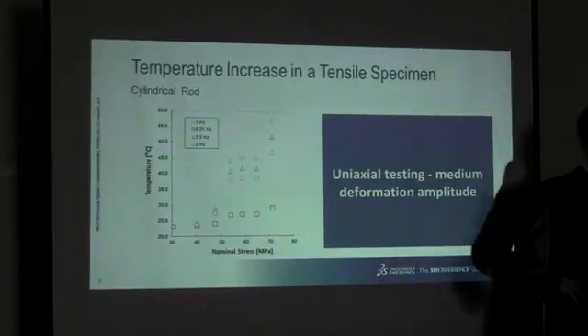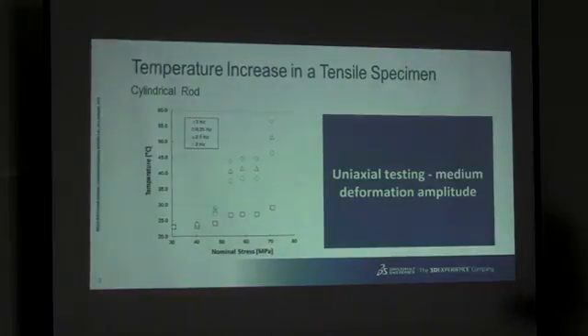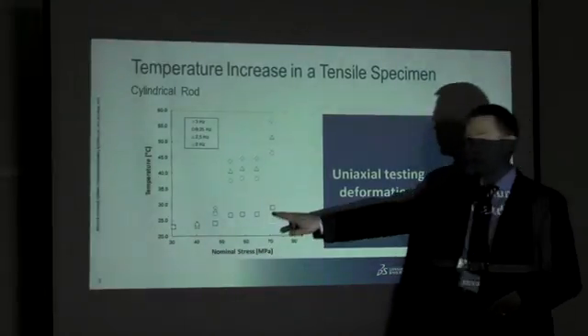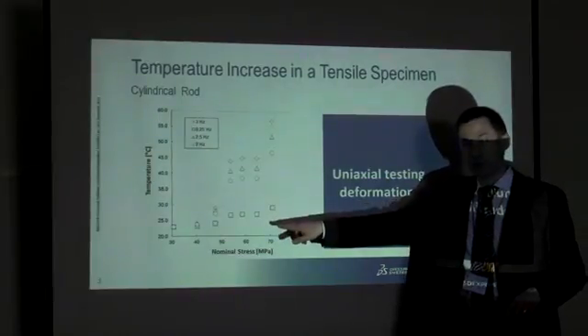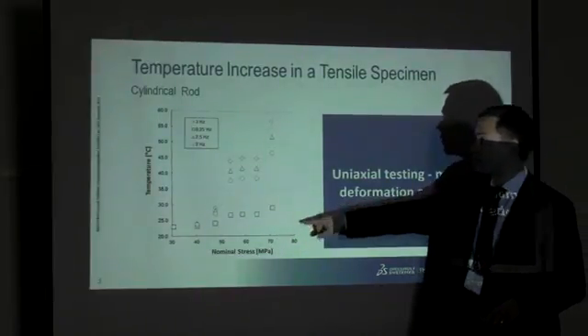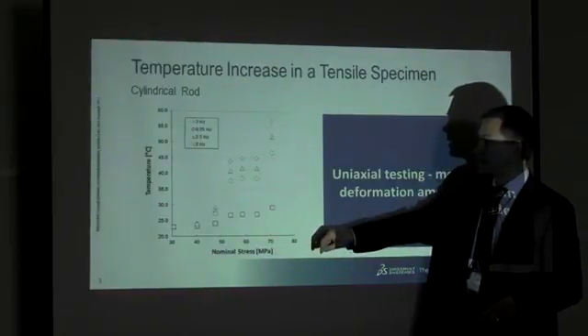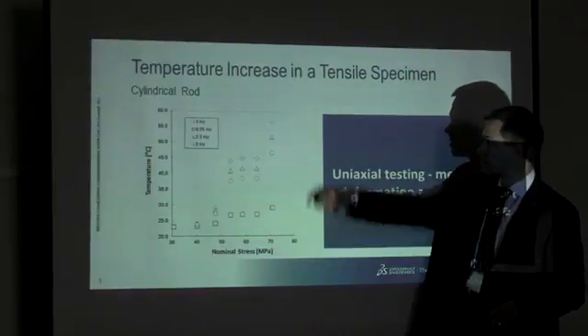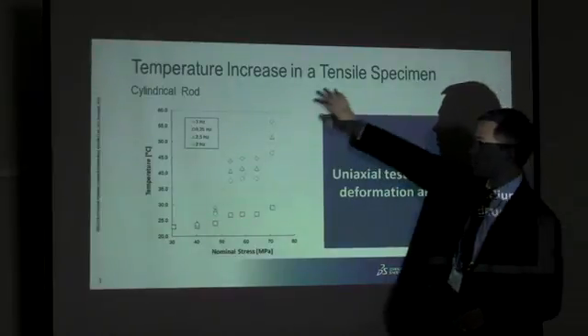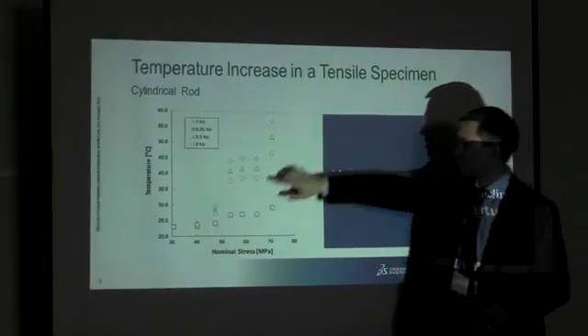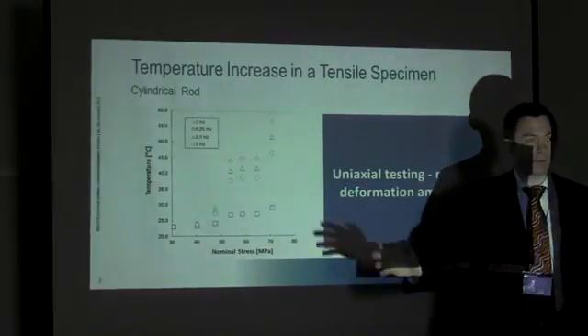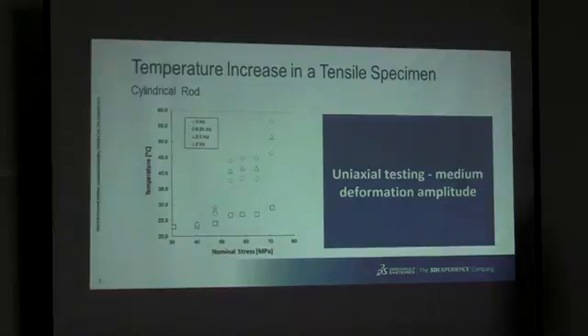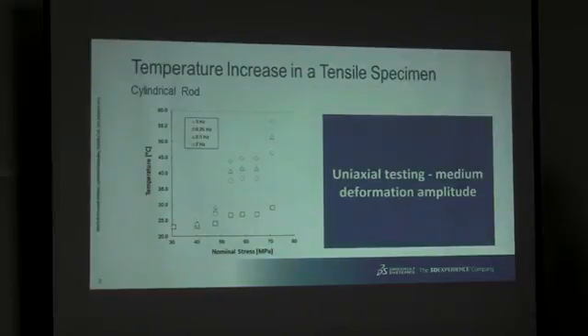And as you can see, we wanted to investigate how low do we have to go in order to not see a temperature raise in the specimen, because we don't want to change that. We wanted to have isothermal conditions. Well, it turns out we have to go really, really low, 0.25 Hertz. If we do that, it takes forever to test the specimen. So we decided, okay, we'll ramp it up a little and see what happens. And it is not entirely unproblematic, because at, say, I'm going to go with the worst and say at 3 Hertz, you actually have a temperature increase of about 27, 28 degrees, which is quite massive. And this is not over a very long period of time.